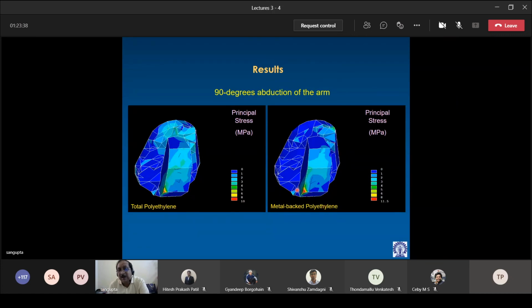But the high stresses in the cement mantle, remember, this is principal stress, these are tensile stresses in the bone cement, and cement has the inherent property of low tensile strength. Okay, so this can be quite threatening, and this can be one of the answers to the question that cement can fail near about the boundary of the implant bone interface. So cement failure, cement crack can be a potential cause of failure already, that is indicated from this stress analysis.